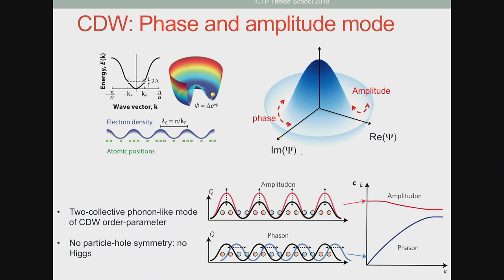So the amplitudon has a gap, and the phase mode is gapless in the case of a clean charge density wave system. So you may say, well, this is the Higgs mode also. Now, this is an amplitude mode of an order parameter, but the analogy with the Higgs mode is less direct than in the case of a superconductor, because in the charge density wave state, there is no guarantee that particle-hole symmetry is preserved. In fact, in general, it's not. So the analogy with the Higgs mode does not really exist in that case.